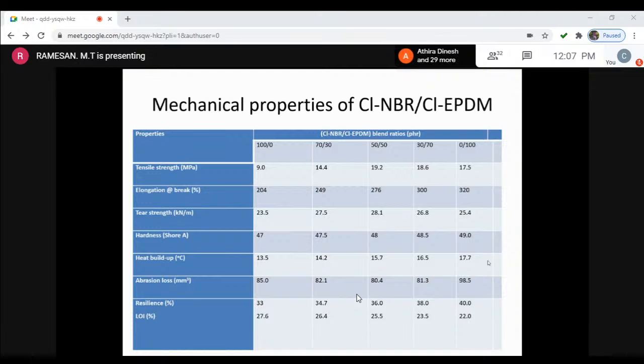abrasion loss is lesser for the 50-50 blend system, which means that there is an efficient interfacial interaction, or strong interaction, between the chlorinated NBR and the chlorinated EPDM. That is the reason for the higher abrasion resistance value.